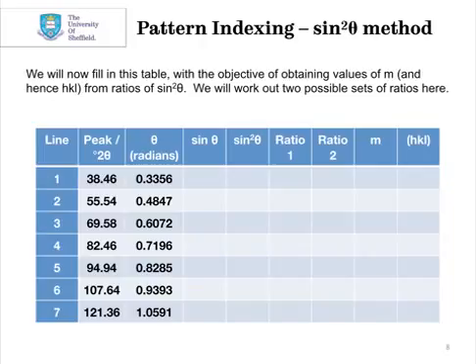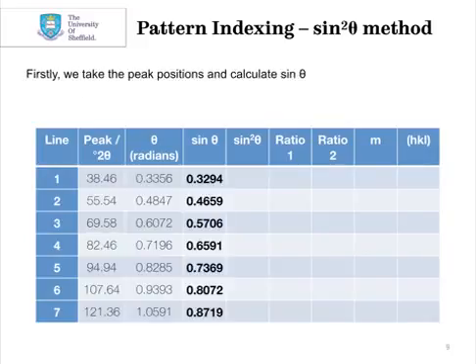We've got the peak positions in 2 theta. I've then filled in the theta position in radians. To get from 2 theta to the theta in radians, we have to first divide the 2 theta values by 2 to give theta, and then convert them to radians using the equation we saw a minute ago. So for example, the peak at 38.46 becomes theta of 0.3356 in radians. The next step is then just to simply take the sine of that theta in radians.